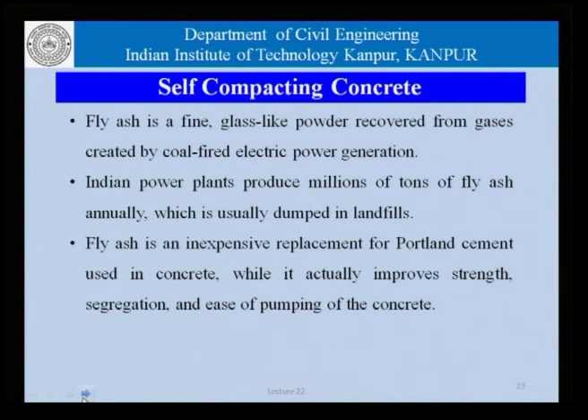Fly ash as such is an inexpensive replacement for Portland cement to be used in concrete, while it actually improves the strength and segregation and also the ease of pumping in the concrete. Of course, it should be noted that not all fly ash can be used. It is not only the size and the reactivity and so on, but also the fact that the properties would depend on the coal which is used, the fineness, the burning temperature, and so on.